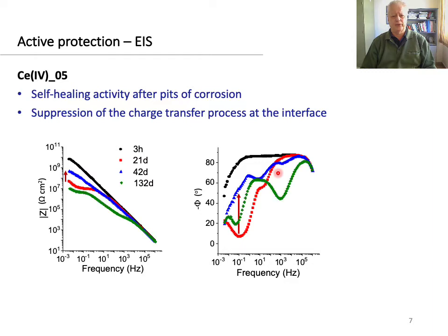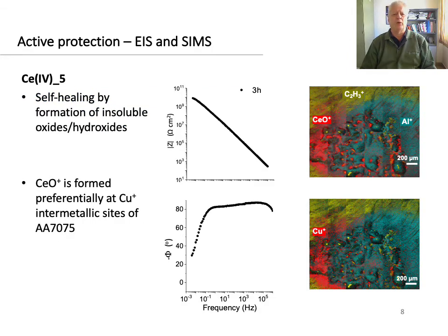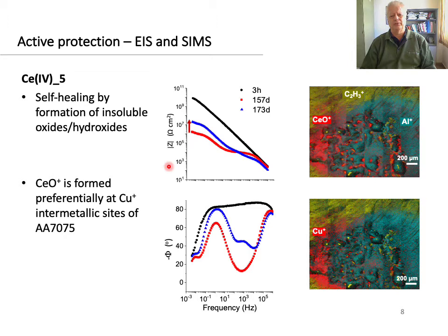This phase angle shows that the main recovery occurs here in the low frequency range, suppressing the charge transfer at the passive layer of the coating aluminum interface. Now, a similar effect was observed for the cerium-4-5 coatings. After the appearance of a pit for 157 days of exposure, the impedance modulus was spontaneously restored by one order of magnitude after 16 days. In this case, the phase angle recovery in the high frequency range indicates the filling of the defects, thus recovering the corrosion resistance of the coating.